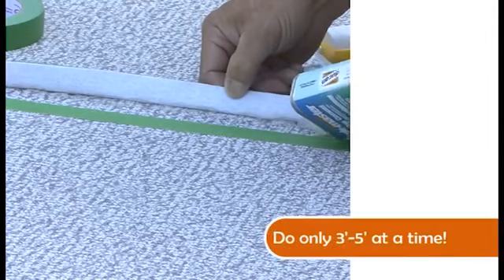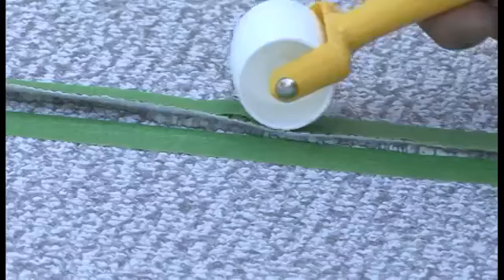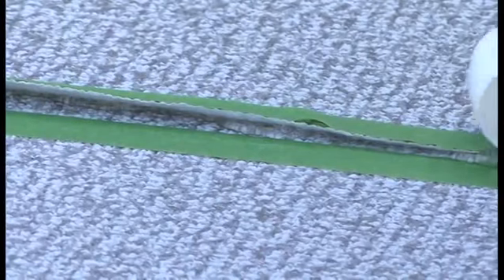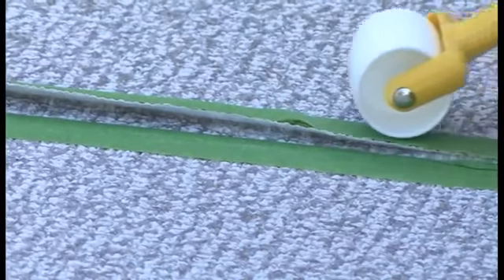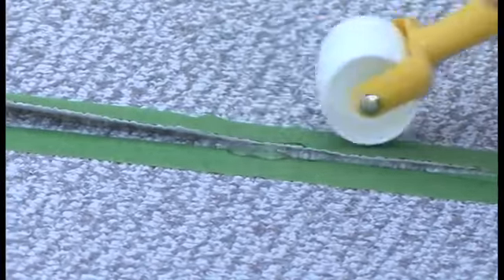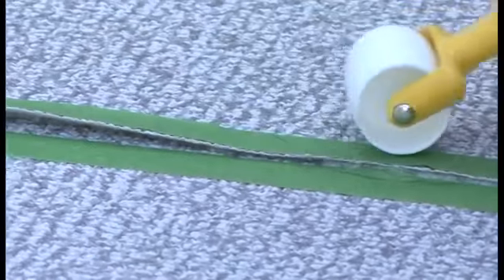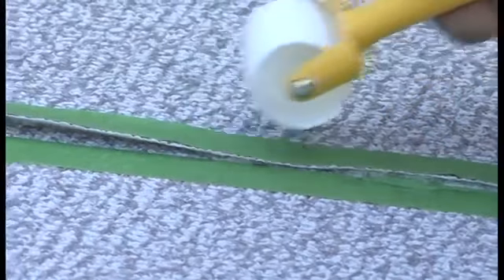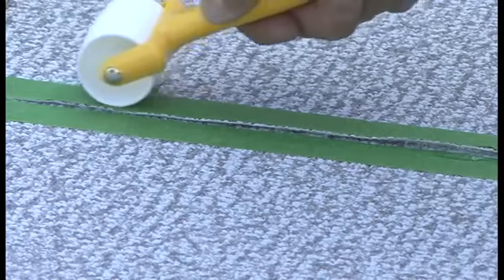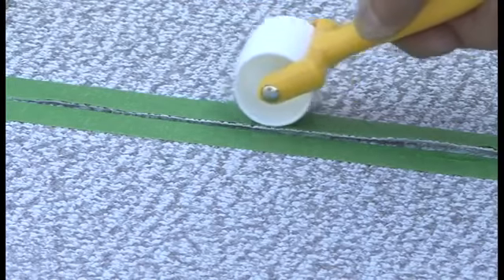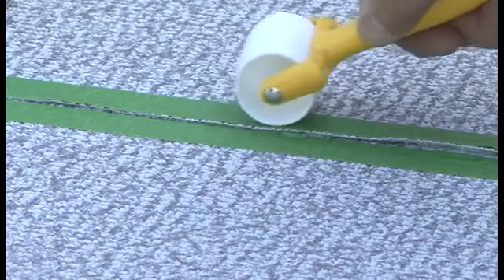Be sure to do only 3 to 5 feet at a time. Take the seam roller and roll over the seam, ensuring the overlap cement comes out onto the masking tape. It is important to be sure that the overlap cement is showing along the edge of the finished seam. This will ensure that the overlap cement has been evenly distributed under the vinyl overlap and will prevent leakage.